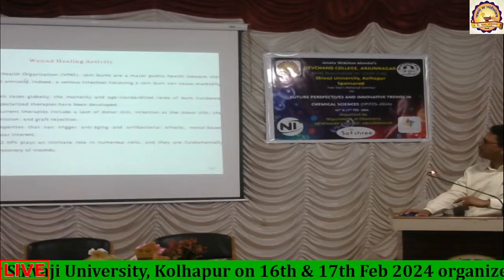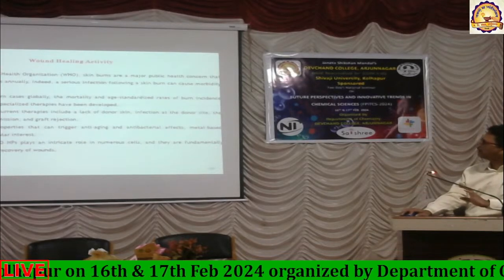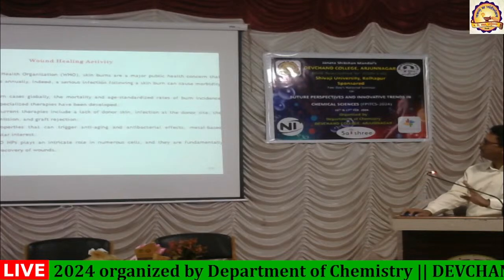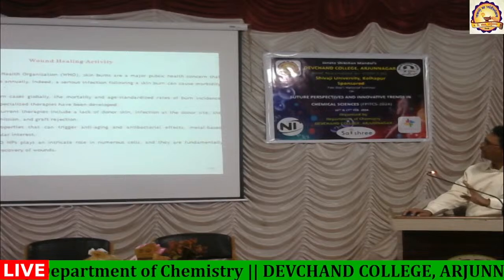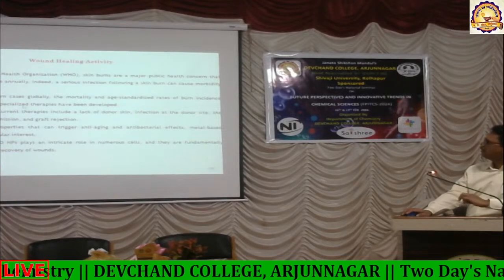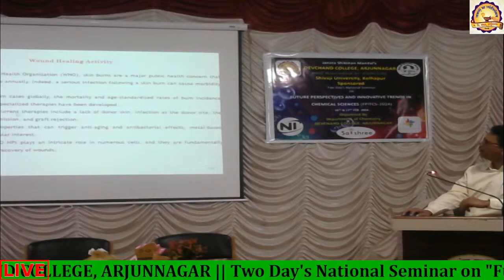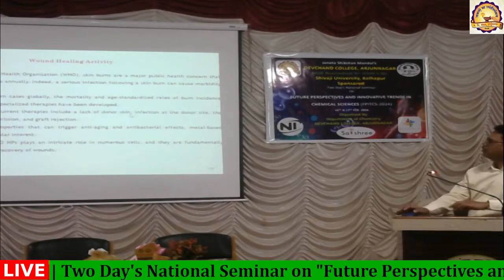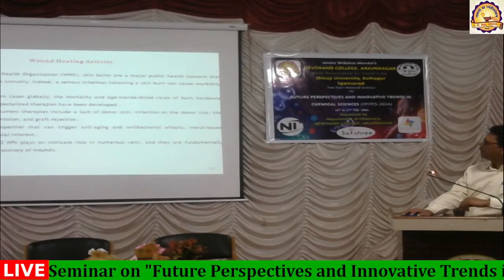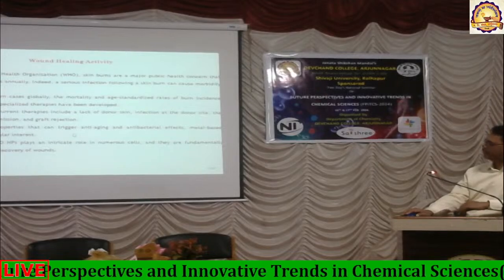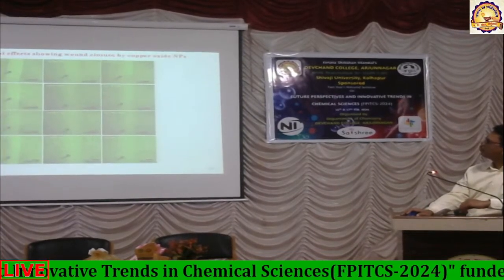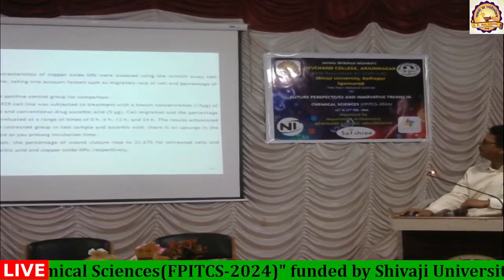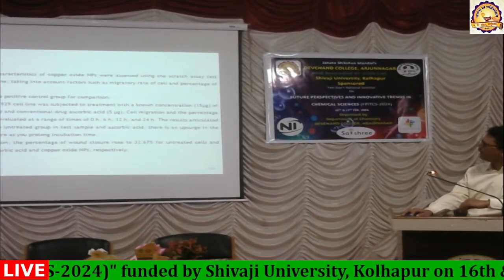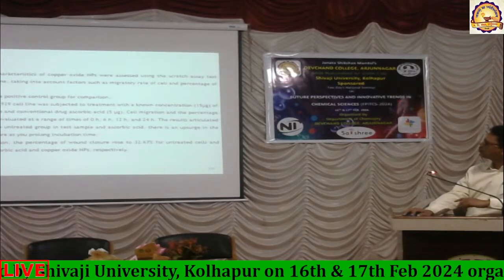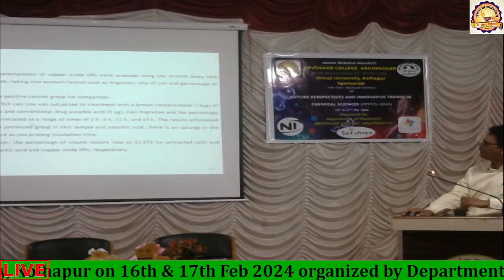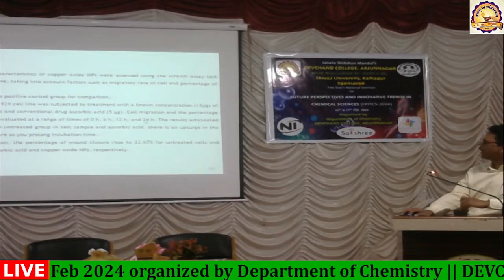And for wound healing activity, we even made use of these copper oxide nanoparticles, where skin burns cause almost 180,000 fatalities annually. The negative aspect of wound healing is the lack of donor skin for burns, and because of this, nanoparticles have been used in the wound healing problem. In view of this, we took sample animal cells, the L929 cell line, and exposed them to the copper oxide nanoparticle that we synthesized, and we evaluated them at 0 hours, 6 hours, 12 hours and 24 hours.